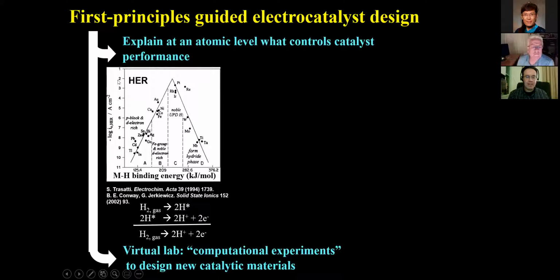And the y-axis here is my rate of reaction, my activity, my current density, where I can measure the rate of an electrocatalytic reaction just in how fast I produce electrons. And that's being plotted versus some property of the catalyst. And empirically, platinum is optimal. And this is an experimental plot where the x-axis is an experimental measurement of how strong each of these metals binds hydrogen. And we find a volcano relationship here, or in other words, we peak with platinum having the highest activity at some intermediate value of our metal hydrogen binding energy, where too weak or too strong gives us a lower activity. So that's an experimental observation.